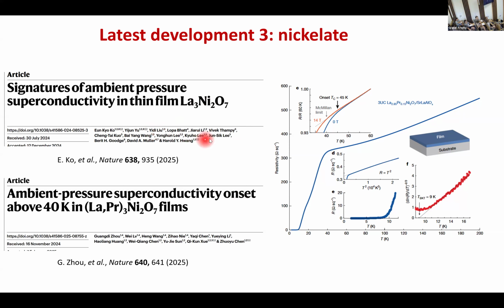And another way to mimic the effect of pressure is to grow this film on a substrate. The idea is that when you grow this very thin film on a substrate, you have the strain effect. This strain effect is just like the pressure. So by growing this thing around strain in the cell, then you can have the right pressure effect, so that this system also shows a relatively high TC. This is a very thin film, so this is really 2D.